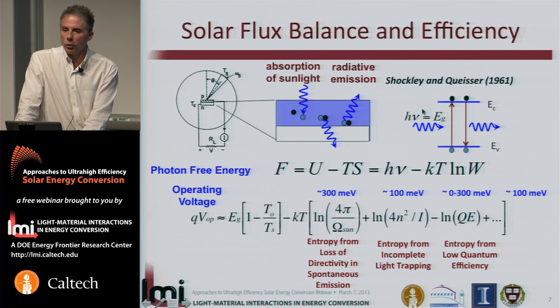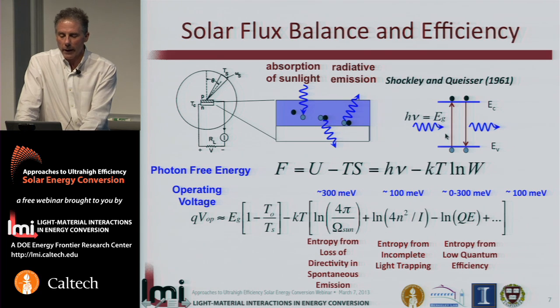And if you looked at this picture naively, you might think, well, the open circuit voltage that I could achieve, the maximum voltage I could achieve, would actually be equal to the band gap energy. And Shockley and Queisser showed that that would be possible in the limit of going all the way to 0 temperature in the radiative limit. And of course, since we don't operate cells at 0 Kelvin, then the practical limits are actually defined by a